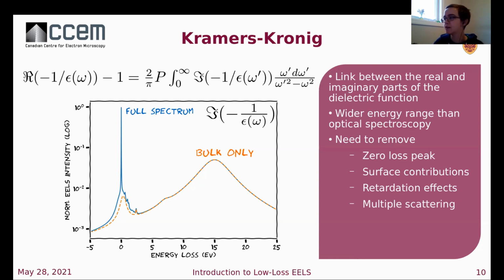This can also be done in optical spectroscopy, but the advantage of using EELS is it has a much wider energy range than optical spectroscopy does. And if we notice this integral goes from 0 to infinity, having a wide energy range can be very advantageous if you want to be accurate in determining the dielectric functions.